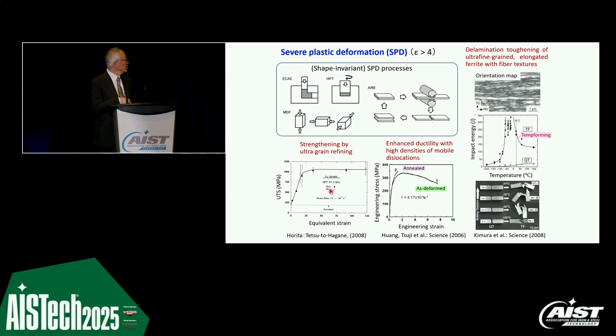We can increase the pure iron to 4 times higher in tensile strength and yield strength. And also, usually we expect work hardening to give us lower ductility. However, by having a high density of mobile dislocations, actually we have better ductility in the as-deformed condition. However, if we anneal that, we lose the ductility.